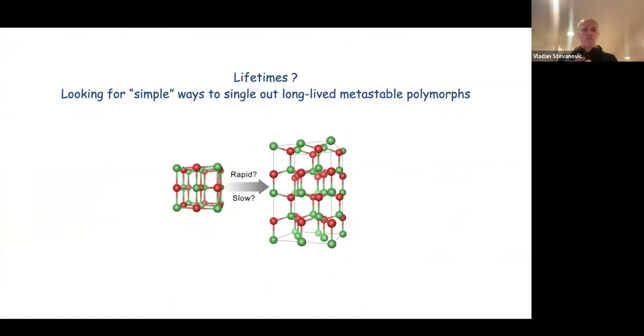All right, so hopefully I provided in these couple of examples some convincing arguments that one can resolve the conundrum of having many low-energy local minima, whereas only few are experimentally observed, by introducing the size of the local minima, or their widths, as a ranking parameter that will distinguish those that are more realizable from those that are less realizable. Depending on what you are working with in the actual experimental situation, one can choose a purely statistical representation of the potential energy surface, where you're just dealing with the sizes of the local minima, or one could choose to also introduce energy and rank things based on full ensemble probabilities and see how that looks.